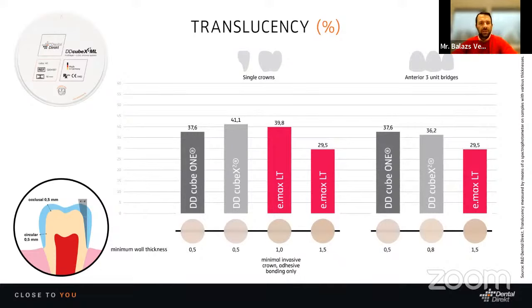It was a nice trend a few years ago, the Emax, but today we have such zirconia materials that have even more material strength, and at the same time we can reach that aesthetic and the strength of the material with less wall thickness. What it means for you as a dentist at the end is that you have to prepare from the natural teeth even less. It's more than enough, 0.5 millimeter. And I, as a dental technician, can say that this is always a critical question between the dentist and the dental technician. How much space do we have in the mouth to create our restoration? And this point, and also the aesthetic point, shows that the direction is also the zirconia material in that topic.